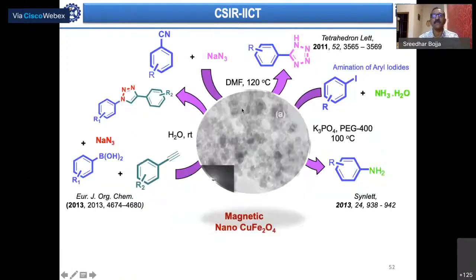And then later what we did, we worked on copper ferrite. The advantage here in iron oxide is that the active species is iron in either 2+ or 3+ form. But when we added copper to ferrite, it means we are having another active species, that is copper, in its either valence state or metallic form. So we have two elements in the material which are active species for this kind of reactions. We initially started with synthesis of triazoles, then tetrazoles, and then these kind of reactions.